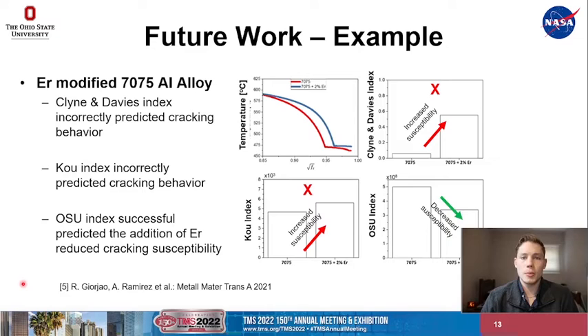On this slide, we show an example demonstrating the advantages of this newly developed solidification cracking index. This was an erbium modified 7075 aluminum alloy, which both Clyne & Davies index and Kou index modeled incorrectly. You can see in the top right that Clyne & Davies index predicted increased susceptibility with the addition of this element, and Kou's index on the bottom left also indicated increased susceptibility with the addition of this element. On the bottom right, you can see that the newly developed OSU index estimated decreased susceptibility with the addition of this element, which is what was actually seen in experimental results. This shows some of the benefit of this system in incorporating the computational fluid dynamics.